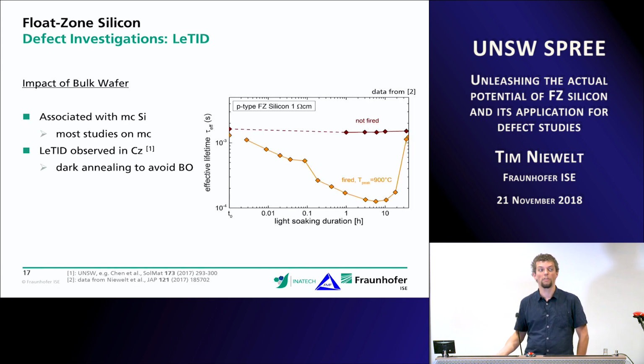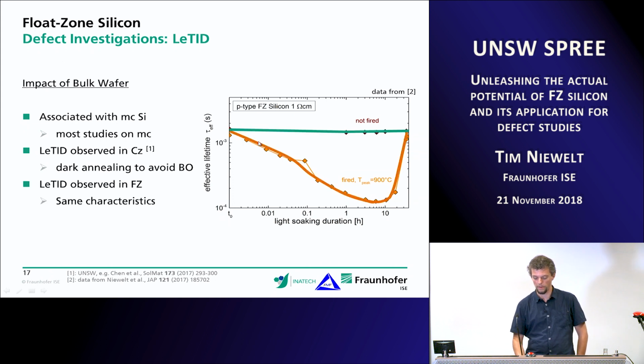And then we started using our float zone silicon to look at the degradation, and we see that also float zone silicon can degrade. And here, this is what I mentioned earlier. We can really ruin the lifetime of a float zone wafer by treating it. And in this case, the LeTID degradation has occurred. We see the typical behavior of samples degrading that have been fired, while sister samples that have not been fired with the same passivation stack don't degrade over time. The treatment conditions that we used here are the standard conditions of 75 degrees C and one sun equivalent illumination. So yes, we see the same characteristics, meaning that the degradation occurs in all material types, so multicrystalline, Czochralski, and float zone silicon.